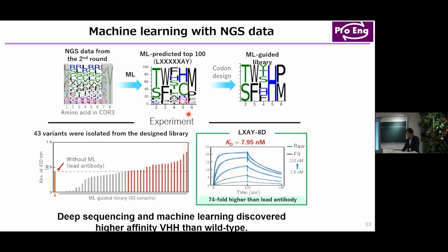So according to this data, we tried to prepare this machine learning guided library as a second library, and then I applied this library to the phage display process. After phage display using this second library, we separated about 40 variants and analyzed the binding by monoclonal phage ELISA. We found several variants which show higher binding affinity than the variant which was found only by experimental promotion.